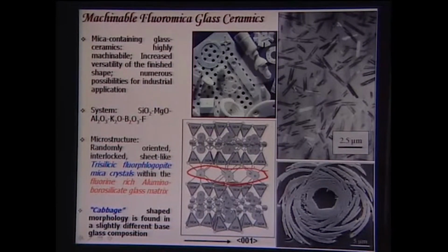Then on top of the potassium atoms, you have the silica tetrahedron, the SiO4 tetrahedron, arranged in a particular manner, and in between the two silica tetrahedra, at the top and bottom, you have the magnesium atoms and the fluorine ions also. These magnesium and fluorine ions are also arranged in a symmetric manner, and the top part and bottom part are ideally symmetric to each other.